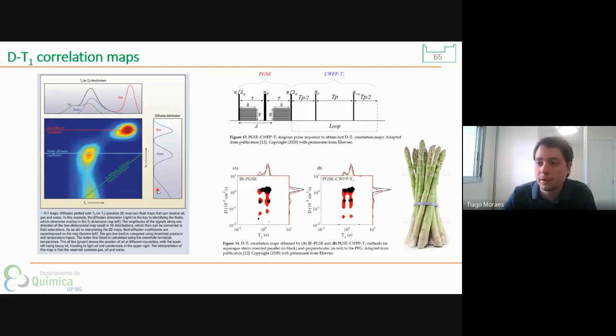So when you use some gradient pulses, you can separate the components based on the diffusion coefficients. And so you produce this type of map, right? The relaxation times as a function of the diffusion coefficient distribution. This is an interesting map that shows maps for asparagus.